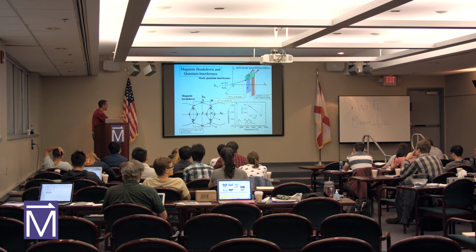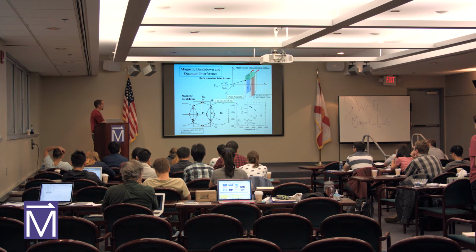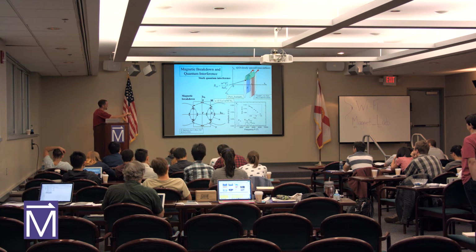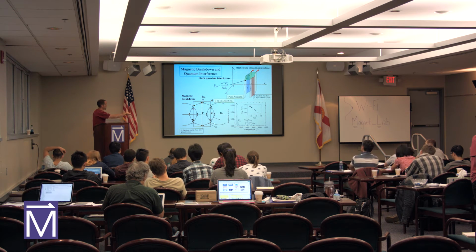If you have a one-dimensional Fermi surface, kind of like this guy shown from the top, and closed orbits in close proximity, you can also get magnetic breakdown. What that means is with a strong enough magnetic field, not only will the electrons go on this closed Fermi surface, but at some point they'll jump off this energy pathway and jump onto another part of the Fermi surface and complete an orbit like this.